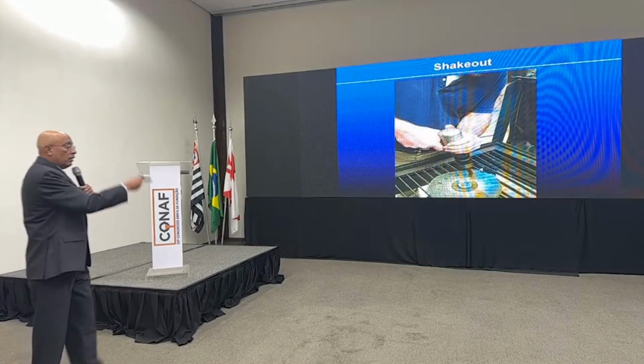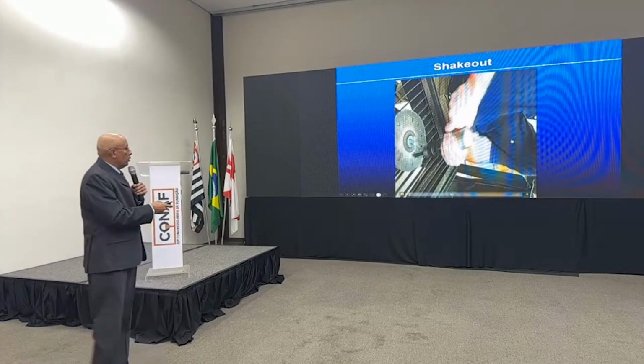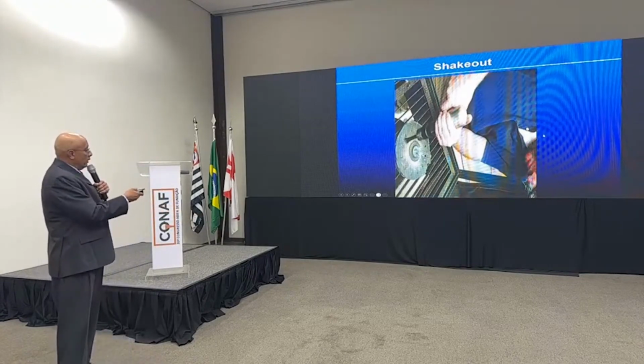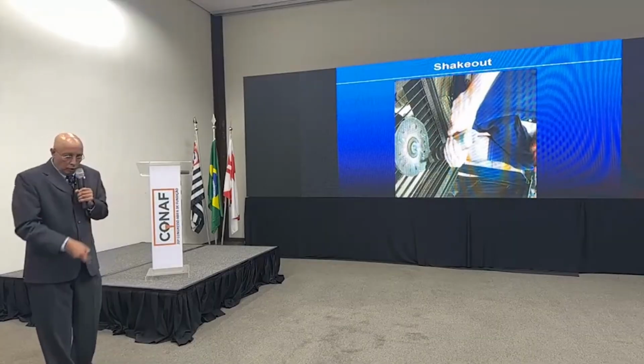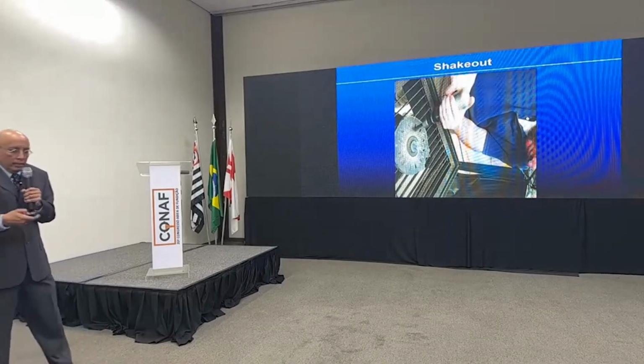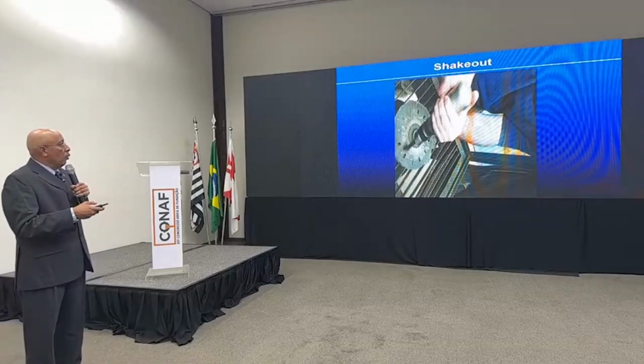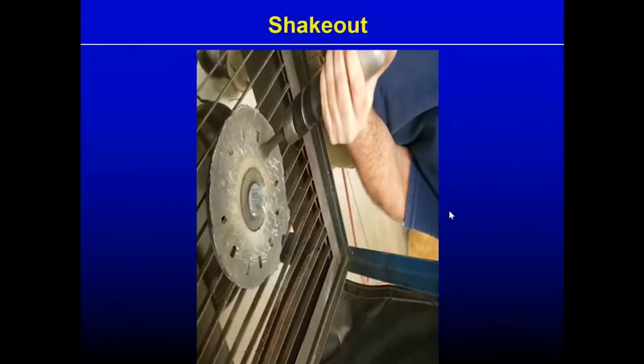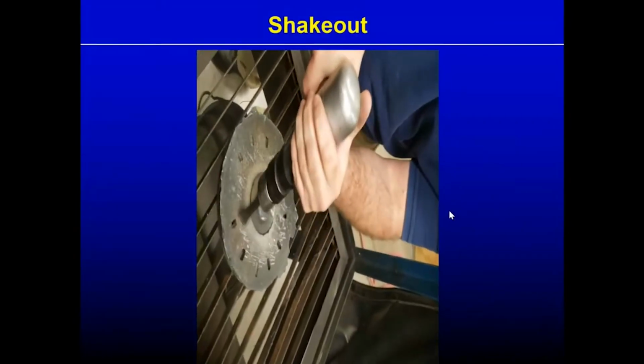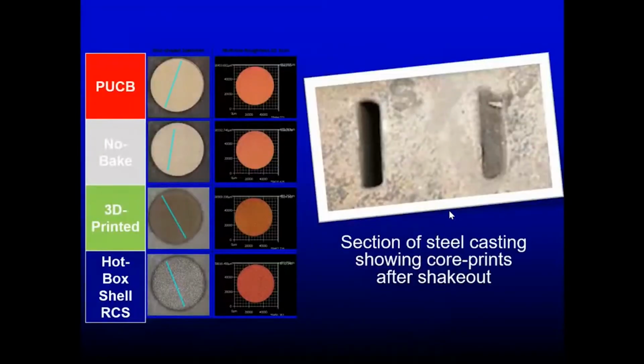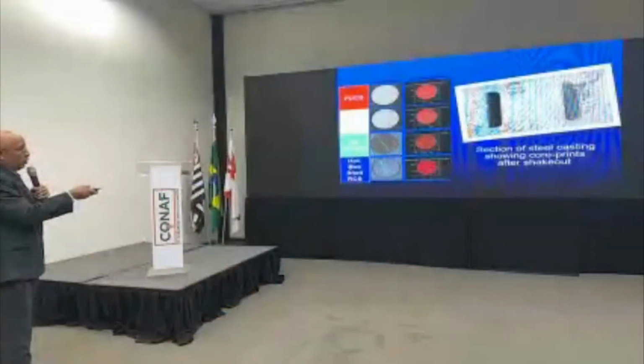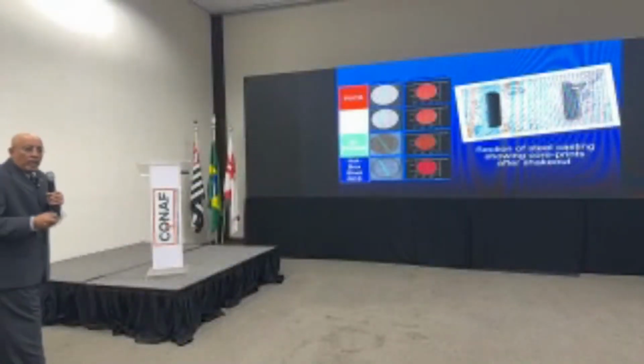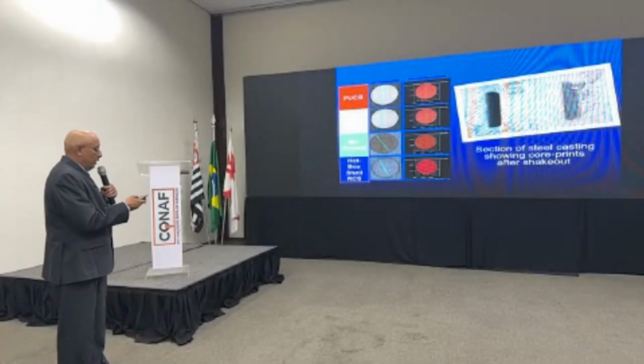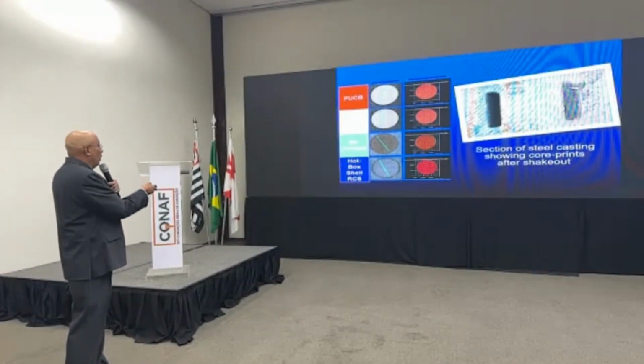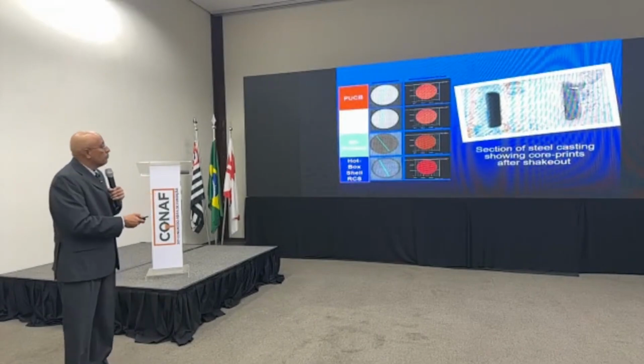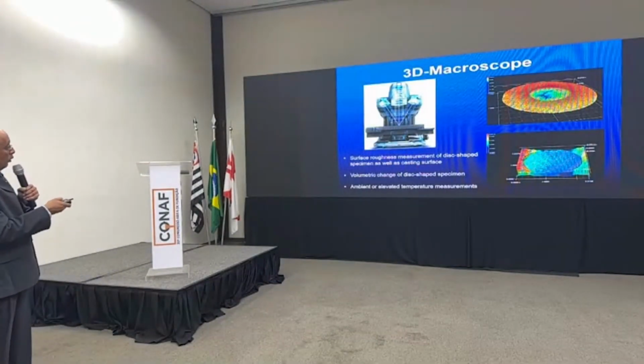This is how we look at shakeout. We put a known amount of energetics, and on the design, the core print allows the sand to fall through. If it remains, we understand, again, from the retained strength, whether or not the sand binder system will lend to these productivity measures for shakeout. Okay, so here I'm showing you a cookie in the donut that shook out, one that didn't. We have this evidence. We can qualify, as I mentioned, whether the systems are urethane cold box, no bake, 3D printed, hot box. We can do that. This is the macroscope that I spoke of.